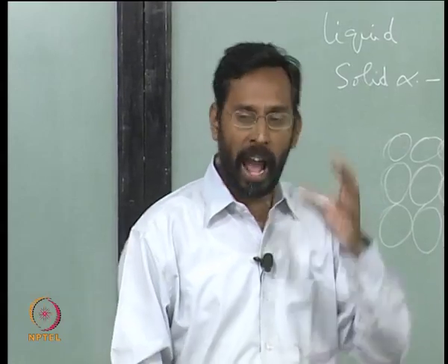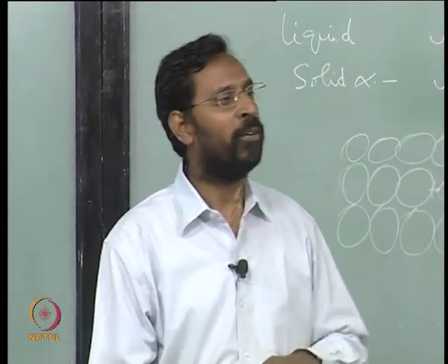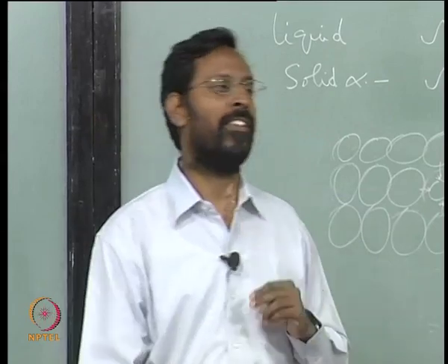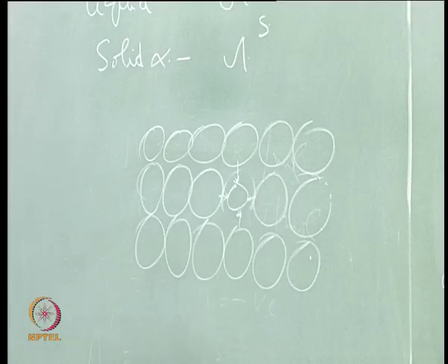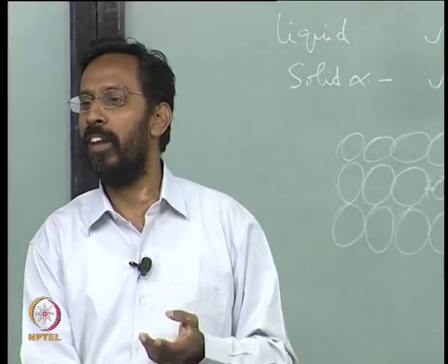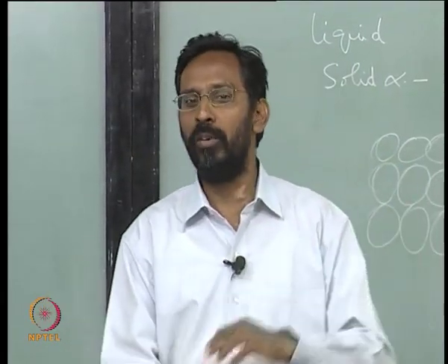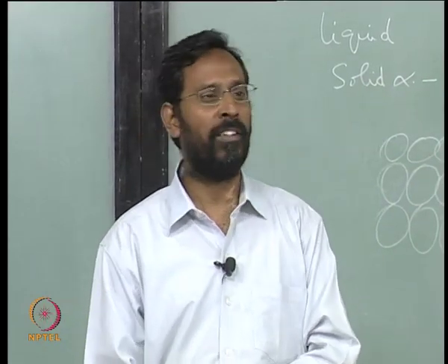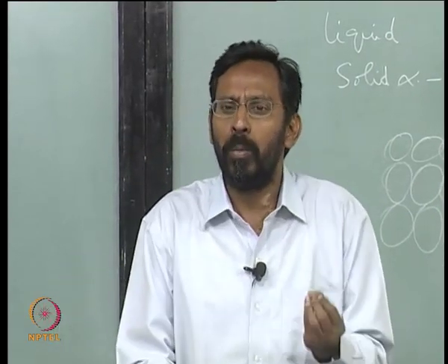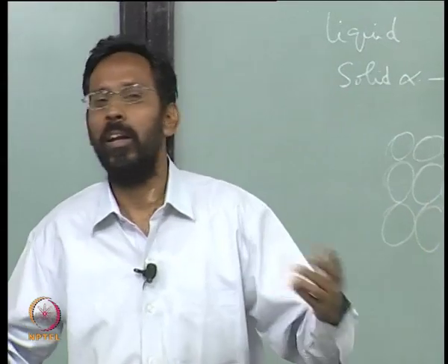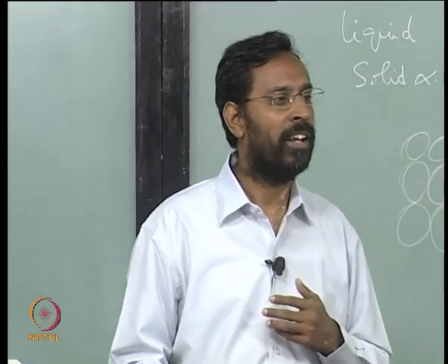And in fact, if you look at the actual carbon atomic size, the size of the carbon atom is much bigger than the void size, and that is the reason why you do not see 100% solubility of carbon in even FCC iron, only 2%. If you compare with many substitutional solid solutions where you have isomorphous phase diagrams, you do not have an isomorphous phase diagram with an interstitial solid solution. It is impossible, because of the only 4 elements that we talk about which can actually go into interstitial solid solutions, which are these elements? Yes, none of them have sizes so small that they can completely dissolve by 100%. The strain generated is sufficient that even if you put a large quantity of this, the strain cannot be accommodated.